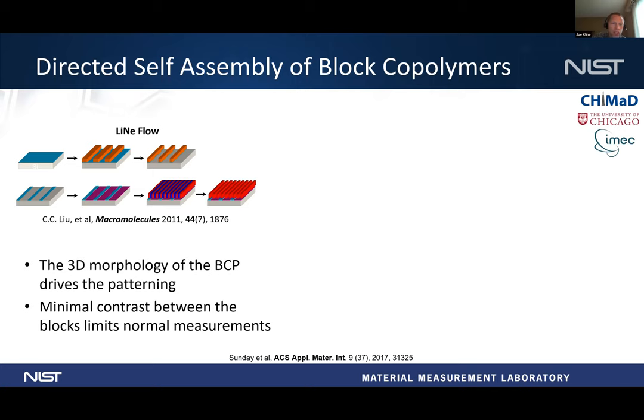You can then put a neutral brush between it, and then you can use that chemical template to epitaxially align a block copolymer that has a pitch that's an integer or an integer fraction of what the original template was that you printed on the wafer. And so you can do 2x, 3x, 4x reduction. And the interesting part, which I'm not talking about today, is that the industry is actually using this at one-to-one for making much smoother lines from patterns that they make from EUV lithography.